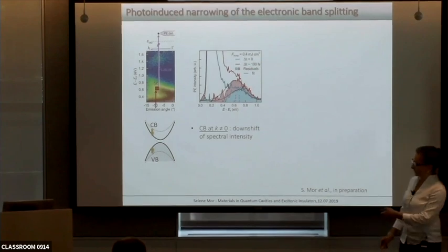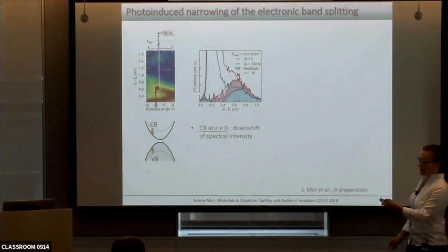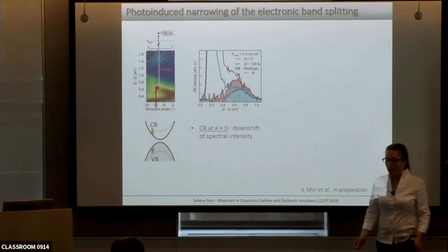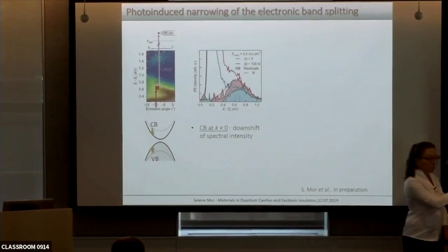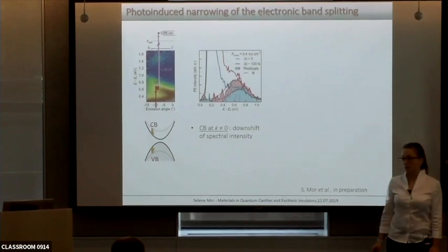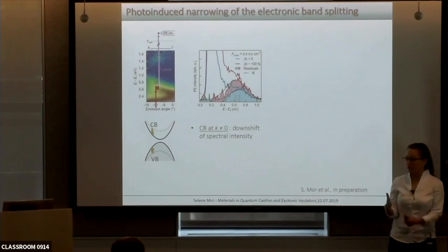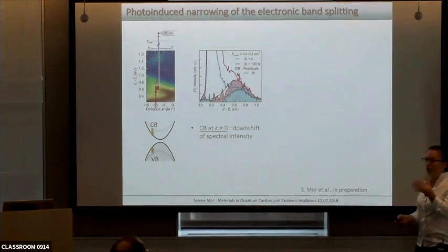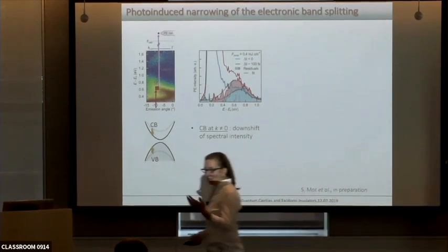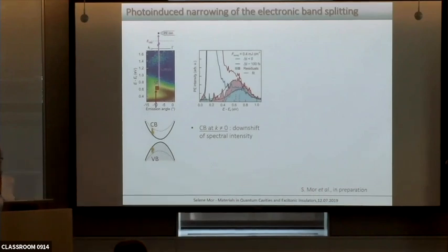So without the first excitation, the conduction band is not only empty, but you cannot reach it with one photon of the probe pulse. Of course, you can have two photons from the same pulse, but this would be a sort of non-time-resolved signature, a static spectrum. So from independent measurements, in a simple picture, you know the number of electrons taken out of the valence band and put into the conduction band, and you know the amount by which the gap narrows.